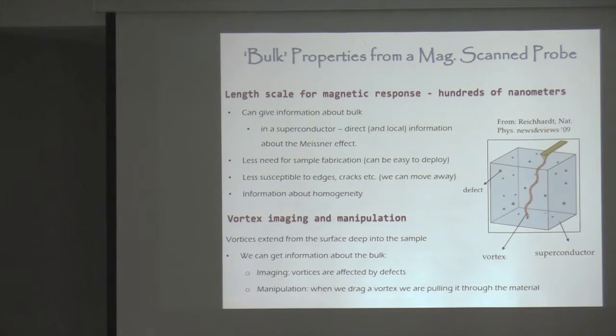We can also look at samples in finite magnetic field when there are vortices, and then we can both see where these vortices are and get information about defects in the sample, and we can also drag them around. A vortex in a field is going to run from one side of the sample to the other side, and then you pull on the top. First of all, if it's sitting somewhere, it means there's something in the bulk. You're not necessarily seeing a surface effect. And then if you drag this thing, you can call it vortex microscopy if you really wanted to. So we play with that a little bit.